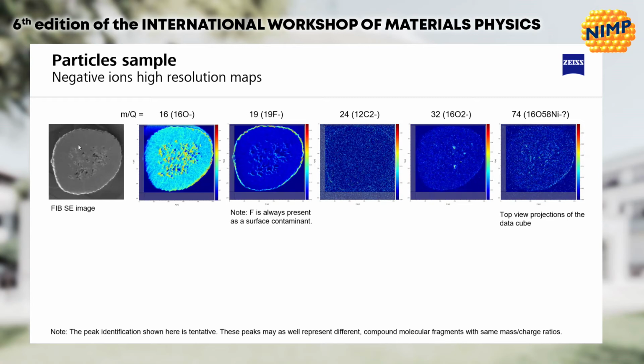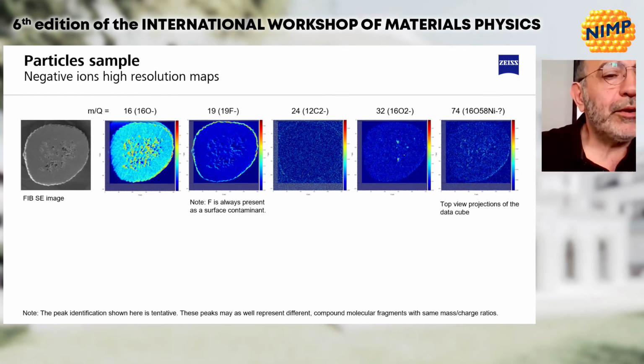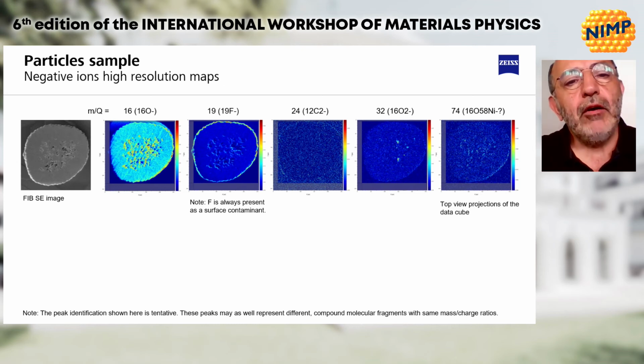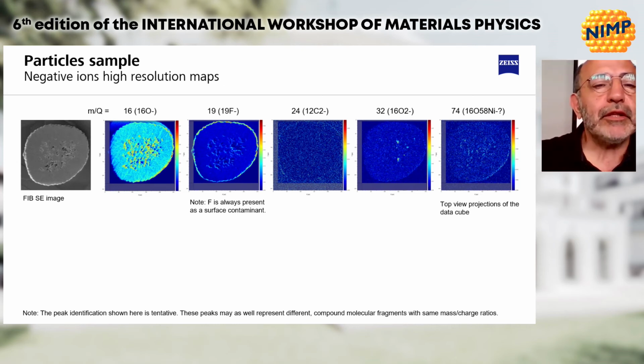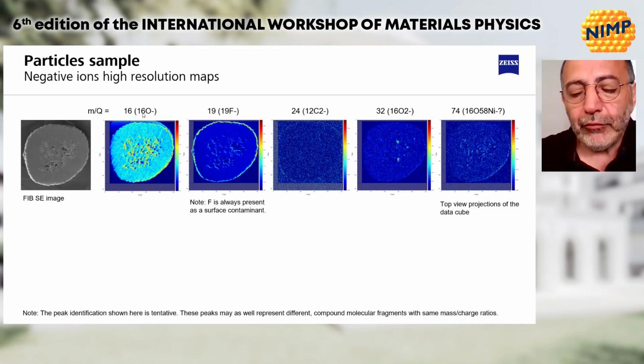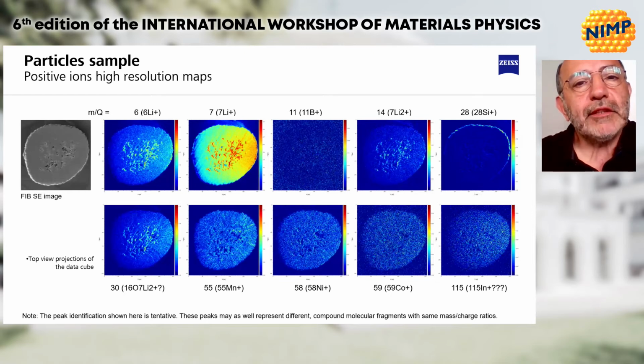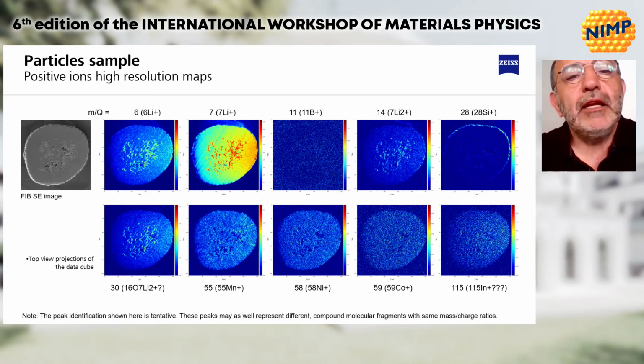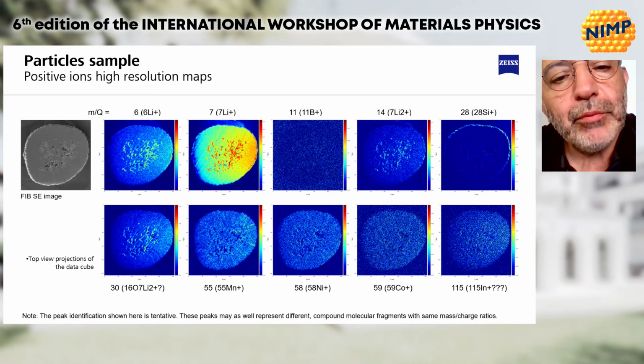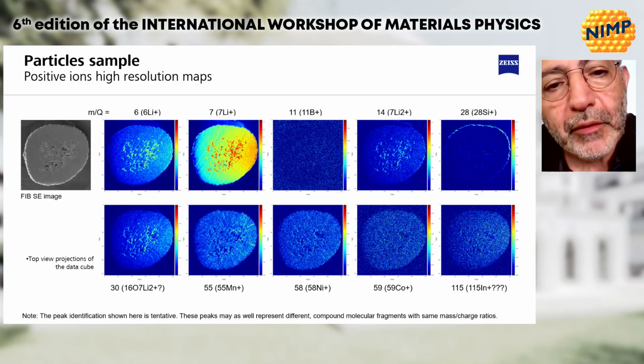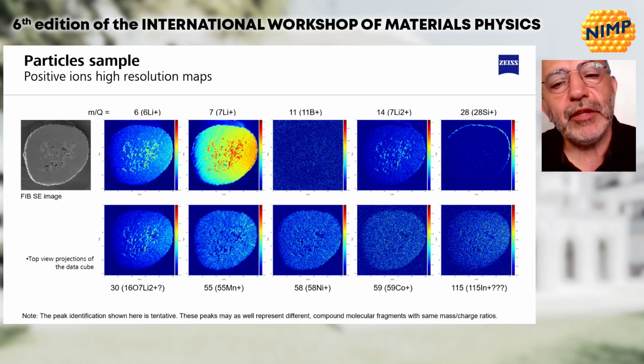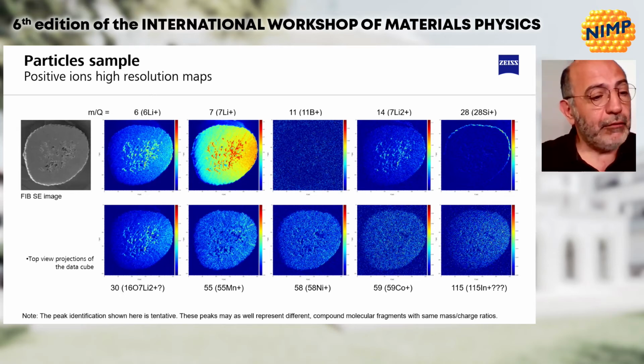On the left, you see the image from the dual beam, in this case the SE image from the FIB, with qualitative contrast information. And now we are starting to select the different elements that we are looking for. We are seeing here the distribution of oxygen, of fluorine, of different kinds of carbon, but also the distribution of lithium isotopes in the sample. In this case, lithium with mass 6 and mass 7, which is very characteristic for this type of battery investigation and degradation after many cycles.